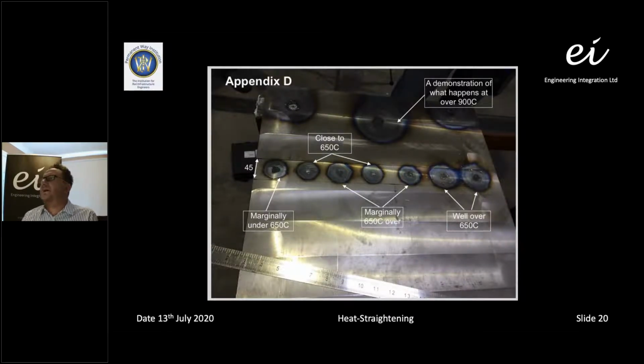This is a test panel that we've undertaken, and you can see there that we've applied different heats to different sections of the girder. And you can see that the circumference of the circle is quite well defined within the steel. You can see there where we've overheated up to 900 degrees, you've got a very wide open dispersal of heat. Whereas when we're working at around 650 degrees, which is our critical temperature, you can see that the circumference of the circles is quite tight, and we've assessed it and agreed that the critical size for the heat straightening process is 45 millimeters, and that's depicted in the lines shown on the test piece. If we go over 650 degrees C, you can see the heating pattern extends outside of that 45 millimeters.